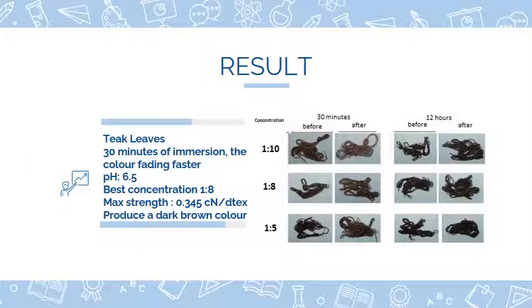In this study, the dyeing process was carried out by two methods, namely immersion for 30 minutes and immersion for 12 hours. These two methods produce different colors. However, the resulting color difference was not significant. The 30 minutes immersion result had the characteristic of the color fading faster when fixed than the 12 hours immersion. This phenomenon occurs due to the acidic nature of alum as a fixator.